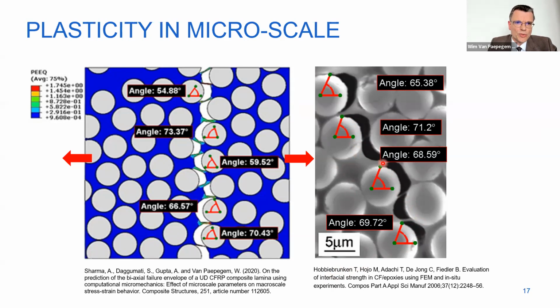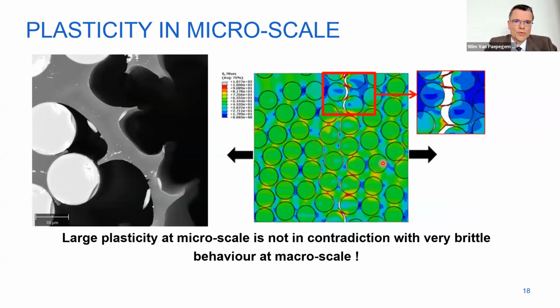This seems like a lot of ductility, but this is not in contradiction with the brittle observation at structural scale or at coupon scale. You see here this plastic deformation. What is the opening here? It's only a few micron because the diameter of the fiber is roughly 10 micron. So at macroscopic scale, this is still very brittle. But we can confirm from scanning electron microscope, here you see what was originally around the fiber and also this part around this fiber. So you do see a lot of plasticity.